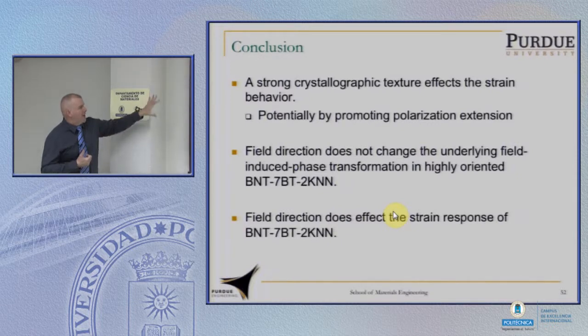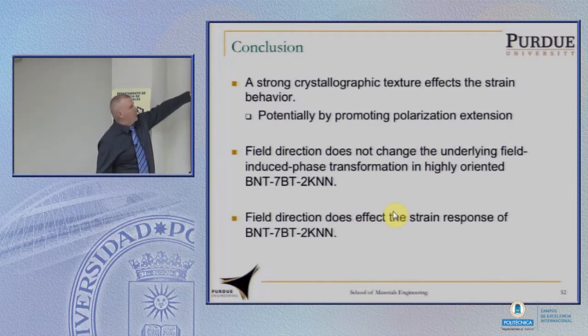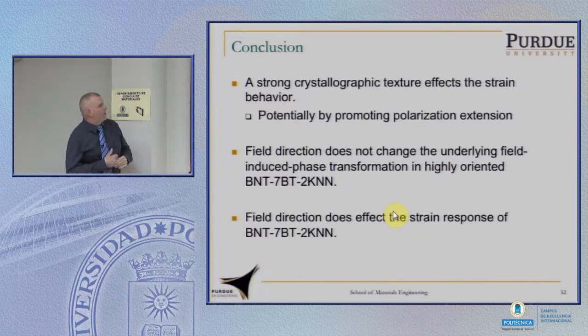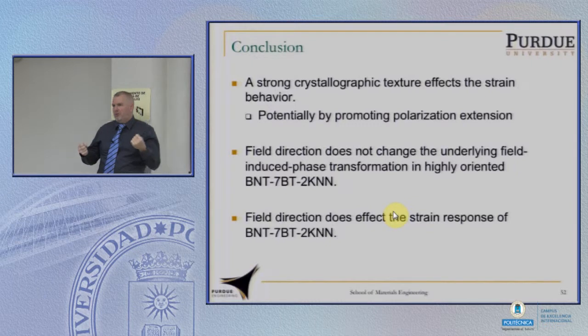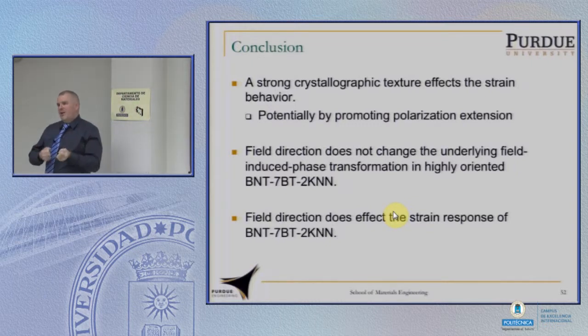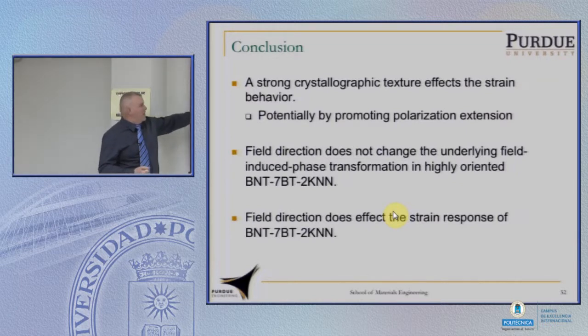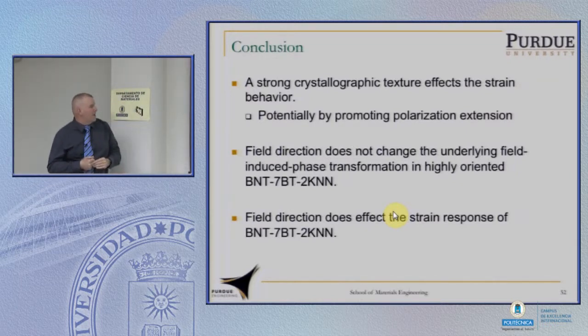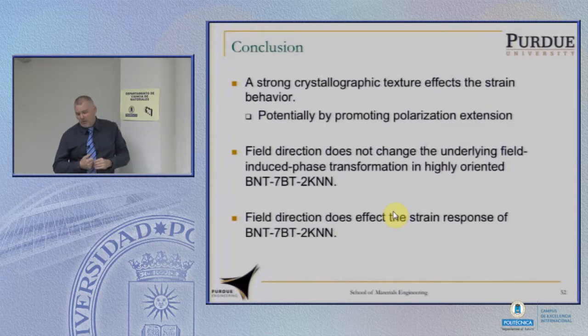The other thing I did not cover as strongly here, but it is true that the field direction does not change the underlying field-induced phase transformation in these materials. Turns out these materials, as you apply field, undergo a phase change that allows you to get the higher strain behavior. And the strain response is not affected very much by changing the field direction for these materials.